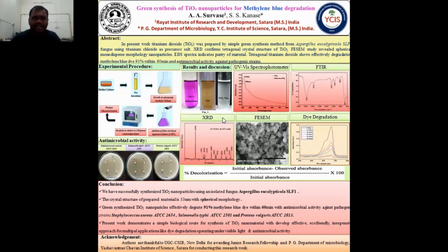X-ray diffraction technique is used for identification of size, shape and nature of nanoparticles. With the help of XRD data, we concluded that we synthesized pure anatase tetragonal TiO2 nanoparticles. We used the Debye-Scherrer formula to calculate the crystallite grain size, which is about 33.89 nanometers.